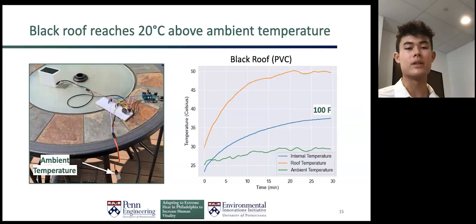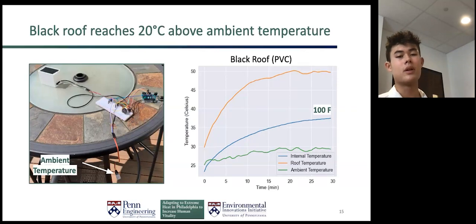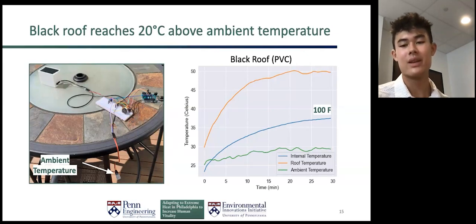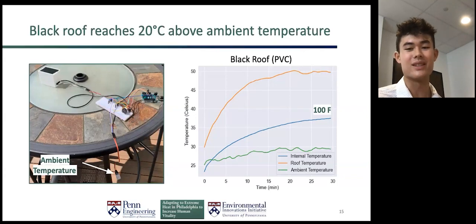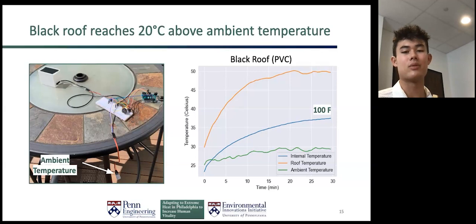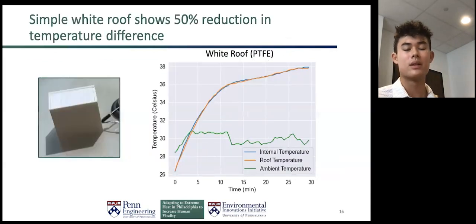And the main change I made for this test was coating the aluminum substrate with black PVC tape to get a baseline value. And after just 20 minutes, the roof heated up to 50 degrees Celsius, and the interior of the box heated up to 38 degrees Celsius or 100 degrees Fahrenheit pretty shortly afterwards. So after that, I swapped out the black roof for a white one to see what the difference would be. And it was very dramatic.